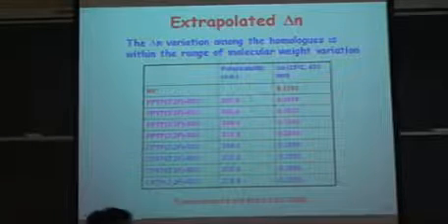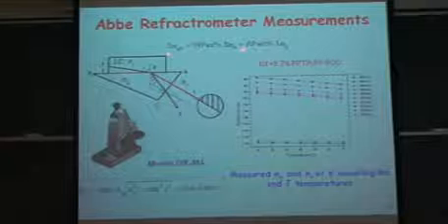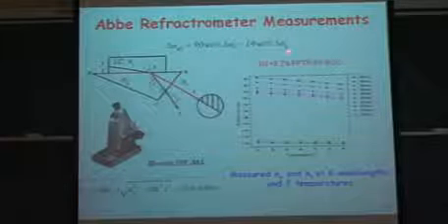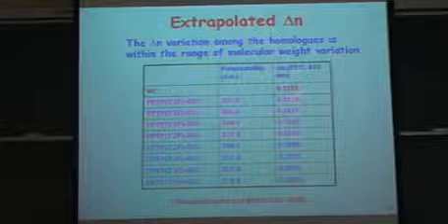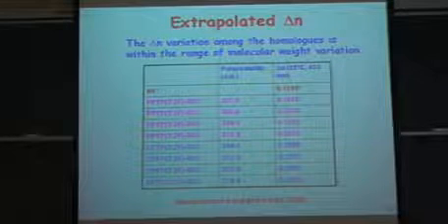So this is the intrinsic data. For the guest-host system, we know the birefringence of the host, and we measure the birefringence of the guest-host mixture. We dope 10% into the host. Then we can extrapolate the birefringence of the guest. So we get this data. For this group of liquid crystals, the birefringence is from 0.38 to 0.34, and for cyclohexane toluene, it was 0.29 to 0.26.